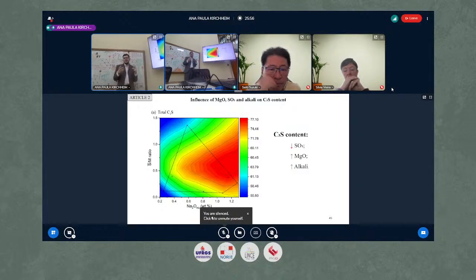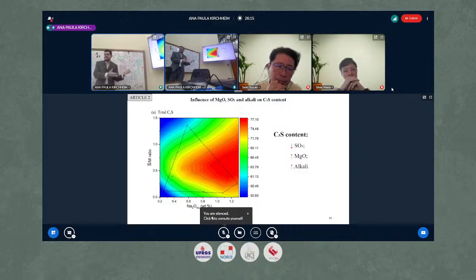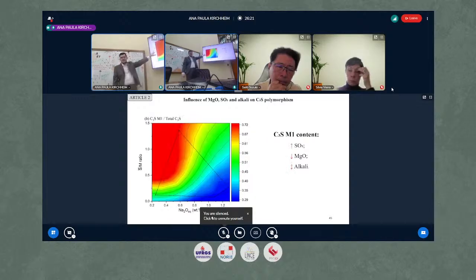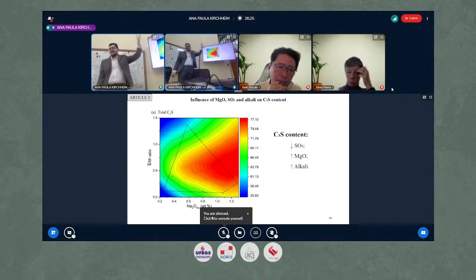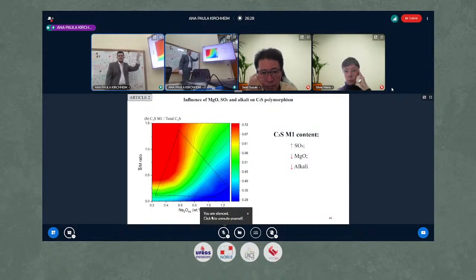This might be due to the reactions between sulfate and alkali. If we have enough alkali, the sulfate will react with the alkali to form alkaline sulfate. If you don't have enough alkali, the SO3 of the sulfate will enter into the silicate structures, stabilizing more belite and less alite. And it's very interesting to see this and compare to this result. We see that what stabilizes the total alite content is the opposite of what stabilizes C3S M1. So to stabilize C3S M1, sulfate is good, while magnesium and alkali stabilize C3S M3.